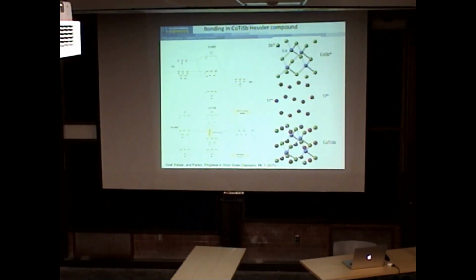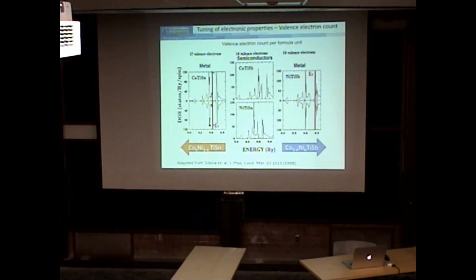You can think of them very simply as, for example, cobalt, titanium, antimony. You can think of this as cobalt antimony zinc blende with titanium stuffed in the octahedral sites. This is titanium 4+, and then you end up neutral, and from the chemistry you should end up with a band gap. In fact, it's predicted to have about a 1 eV band gap. So cobalt titanium antimony and nickel titanium tin, with 18 valence electrons, are normally semiconducting, and if you add an electron you go n-type, or take one away you go p-type.